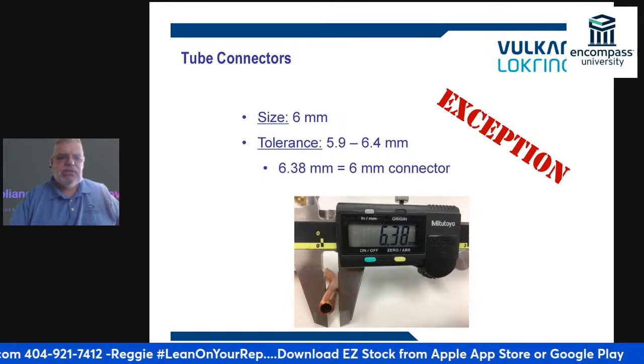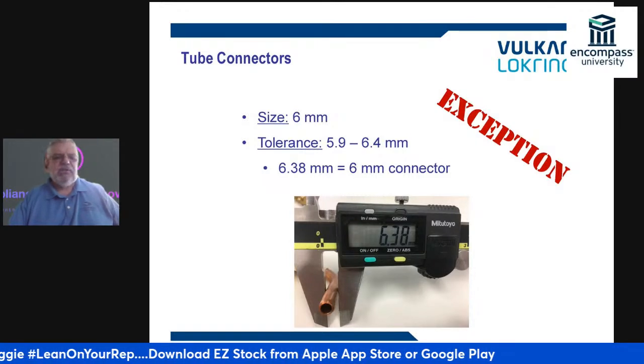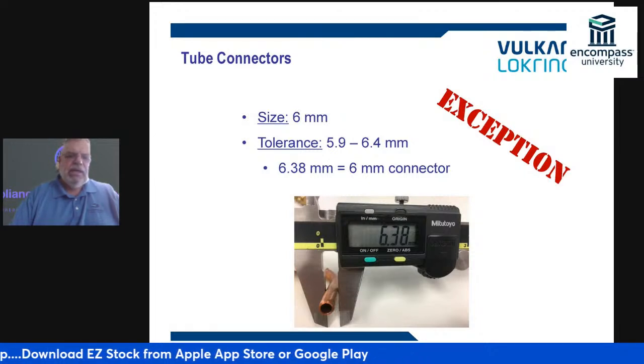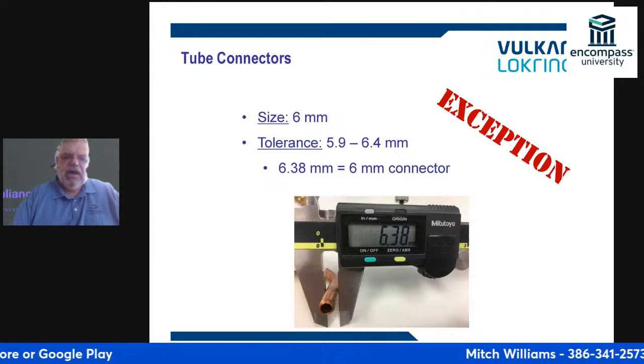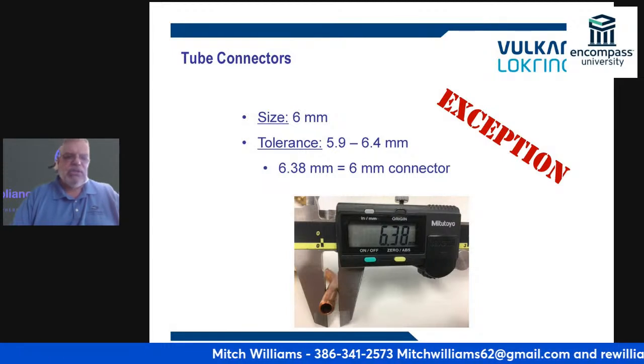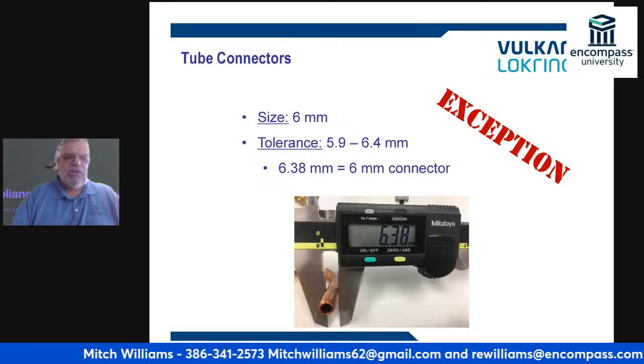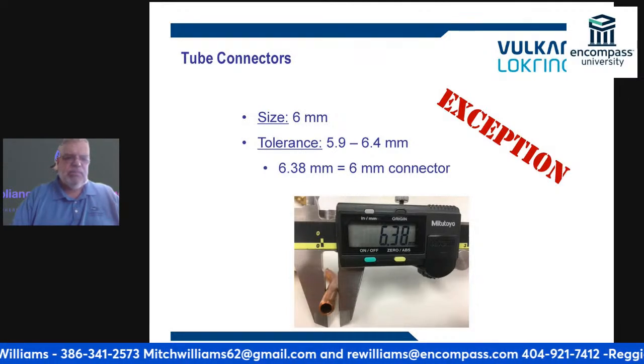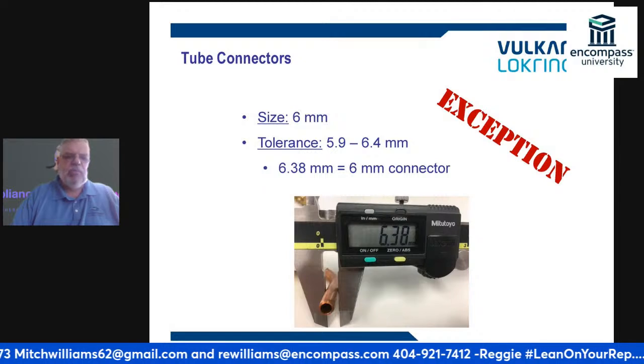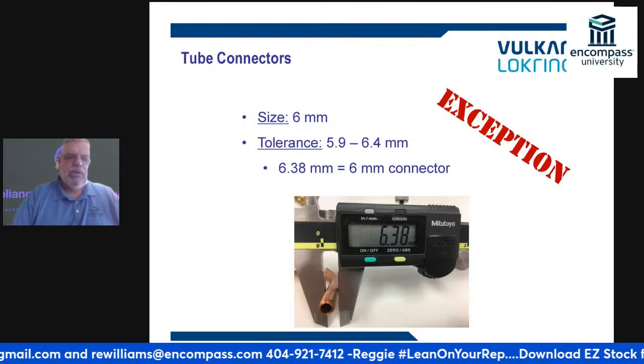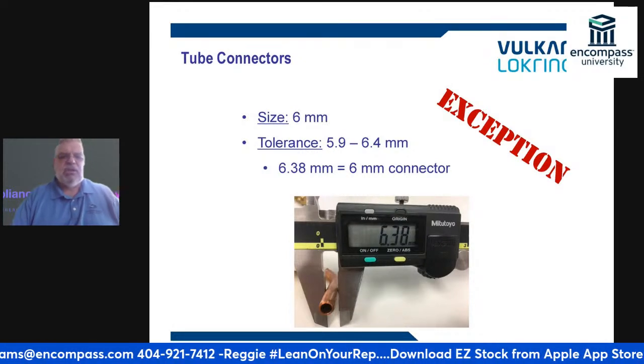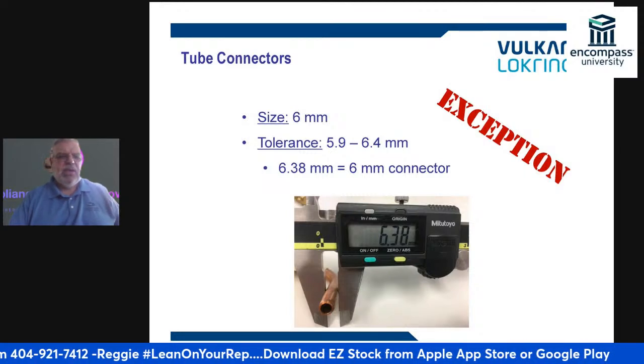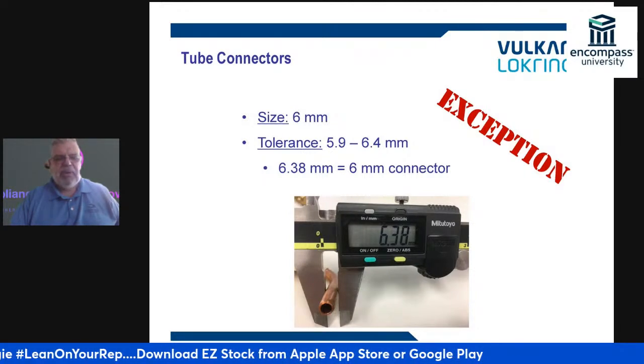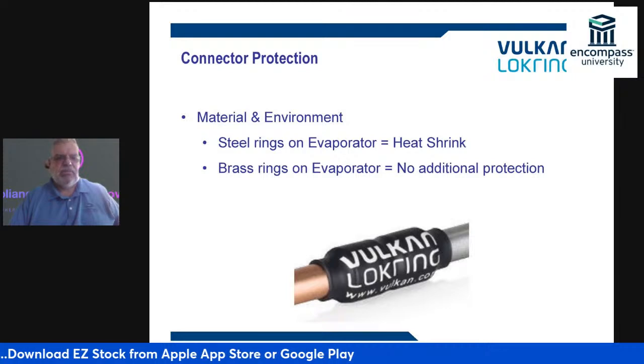Okay. 6 millimeter. My tolerance of a 6 millimeter tubing is 5.9 to 6.4 millimeters. If I have a 6.38, which this one is showing, I'm going to use a 6 millimeter connector because it falls within that 5.9 to 6.4, because it's 6.38, which is less than 6.4. So that makes sure that I have my correct connector.